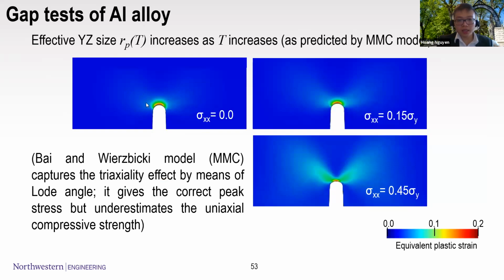And this change is aside from the increase of the yielding zone when you have a larger sigma XX here. And from using a plastic damage model by Professor Bai and Professor Wierzbicki at MIT, we see some qualitative increase in the yielding zone size here, which reflects the fact that GF increases with the sigma XX.